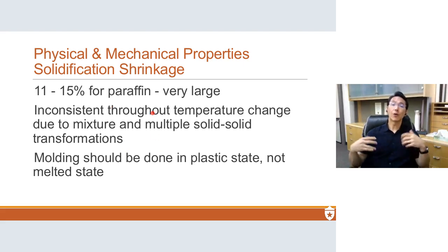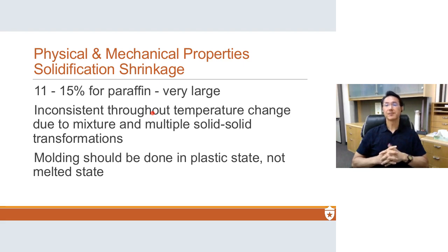Now, of course, most materials shrink when they solidify, right? But there are a few that do not. Ice is one. So when you go from a liquid to a solid, ice actually expands. Silicon, bismuth, antimony, and gallium all actually expand when you go from a liquid to a solid. So not all materials shrink when they freeze, okay? But anyway, for waxes, our problem is the shrinkage, right? Furthermore, the change in dimension is not consistent throughout the temperature range, okay? And that's because you have so many different mixtures of different chemicals and polymers in there. And it gives rise to multiple solid-solid transformations that we will look at. And this allows us to mold waxes in its plastic state, not in the melted state. Okay? And we'll talk more about this.